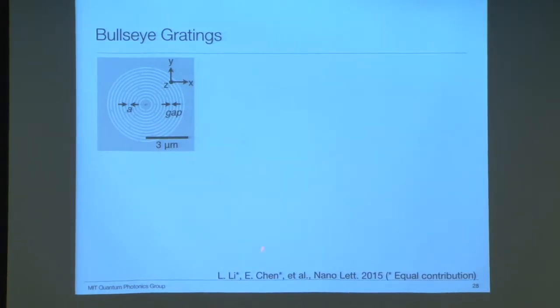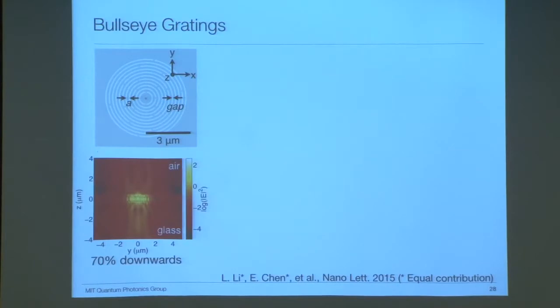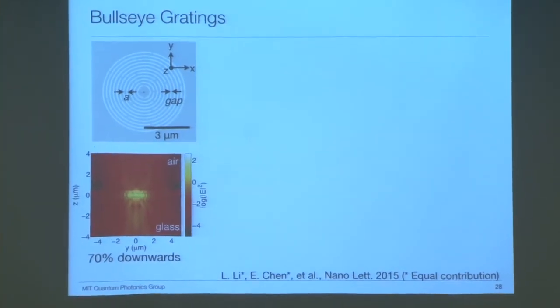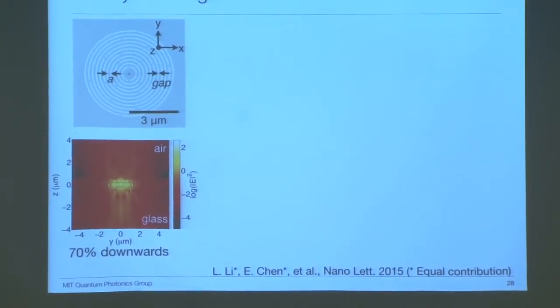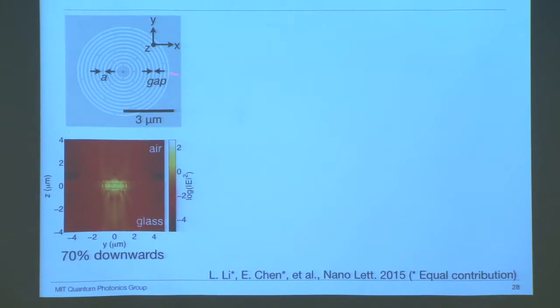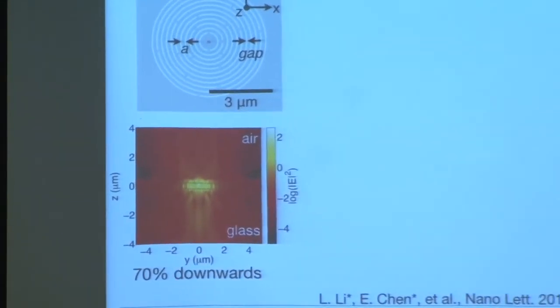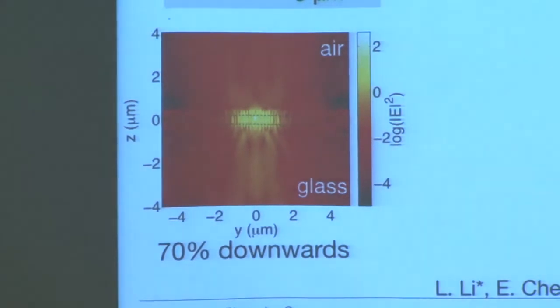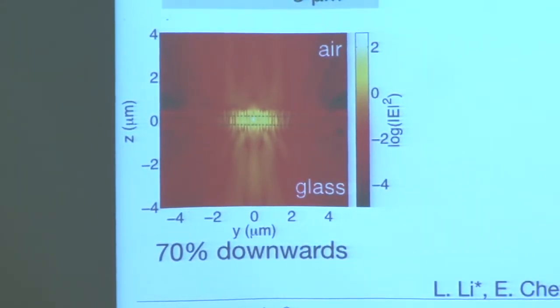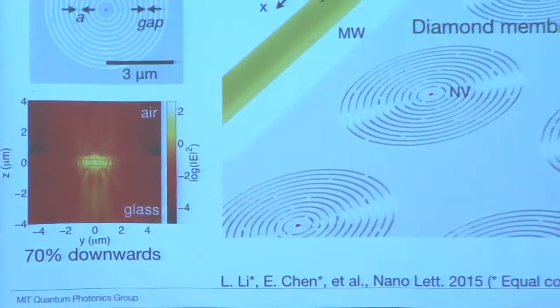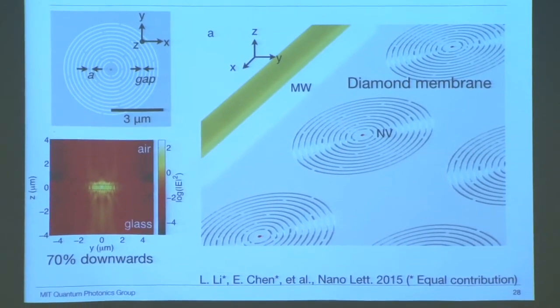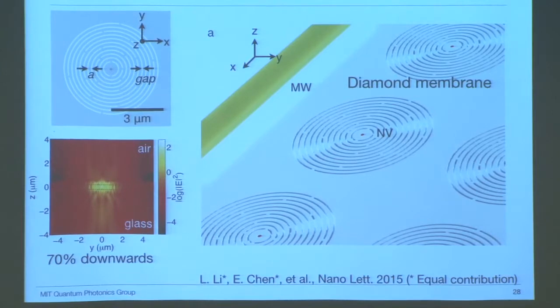These bullseye gratings consist of concentric slits fully etched into diamond membranes. The periodicity of these slits satisfies the second-order Bragg condition. We placed these bullseye gratings onto a cover glass, and we find that the photoluminescence from a single NV is mostly emitted through the cover glass into an oil objective lens and collected. That's about 70% of light. Then we fabricate this diamond membrane with bullseye gratings and place them onto a microwave strip line for both optical and spin measurement.